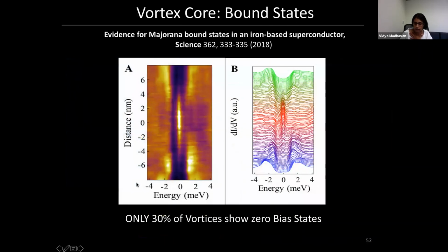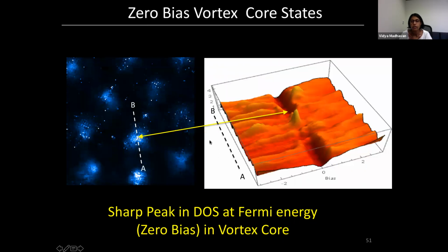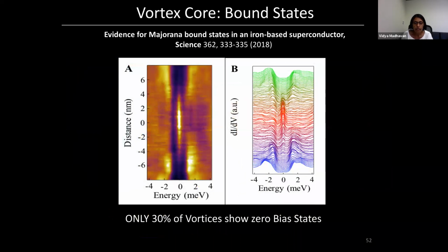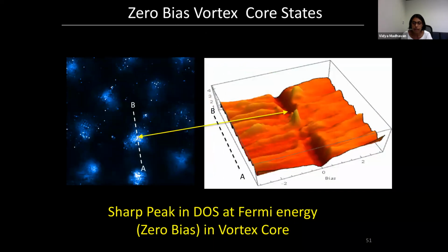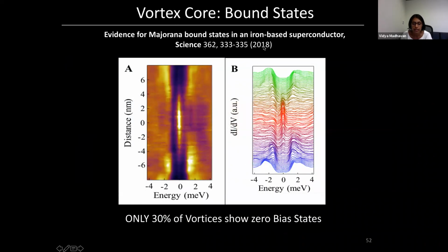Now, if you go to the center of one of these vortex cores, what you find is a sharp peak in the density of states right at zero bias. And theoretically, that's exactly what you expect for a Majorana bound state. So in fact, this experiment was not first done by us. This data is ours, but this experiment was done in 2018, where they measured the same material and found that only 30% of these vortices that I showed you earlier show these beautiful zero bias peaks. And the others show peaks at different voltages.